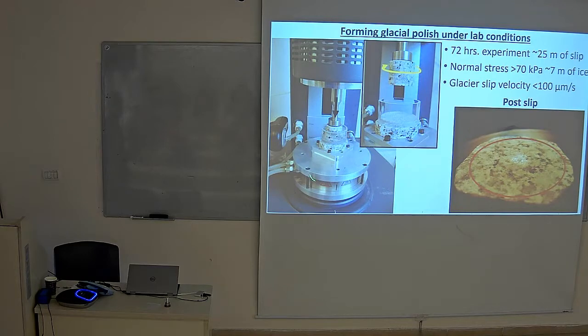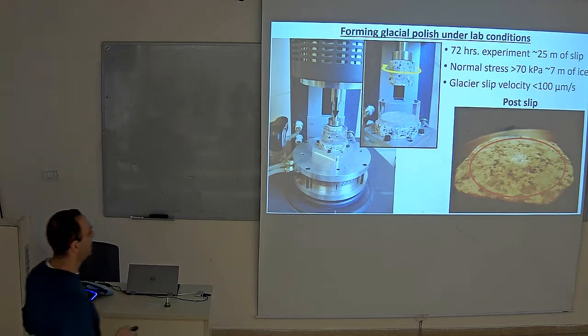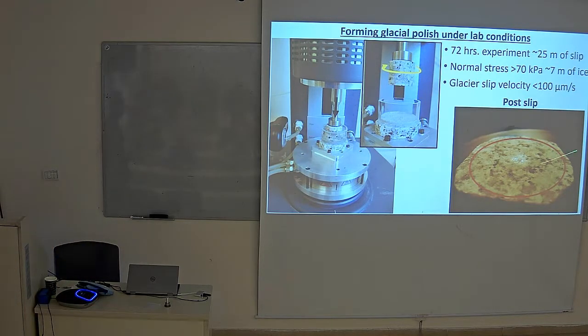So this is a rheometer that's supposed to measure fluid viscosity. However, we are using it for other things, like here a kind of rock shear experiment and granular materials. I glued a slab of granite from Duff Dome to the upper part, put a static slab at the bottom, glued a glass jacket, put inside crushed material from the same granodiorite, stressed it, and then added water and ran it for 72 hours, which is about 25 meters or more, depending on the experiment. Normal stress of about 70 kilopascal, very low normal stress, about 7 meters of ice. And the glacial slip velocity, which is usually below 100 microns per second, is exactly the velocity I ran here. And what we get after we open the surface is obviously a polished patch.